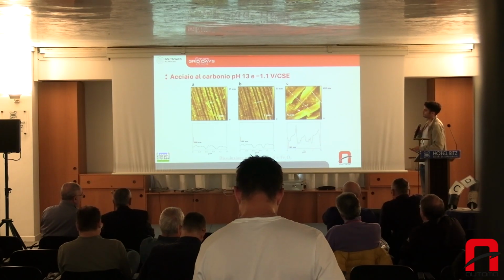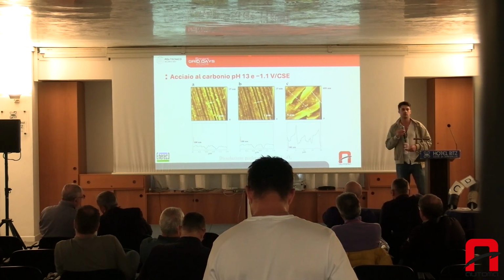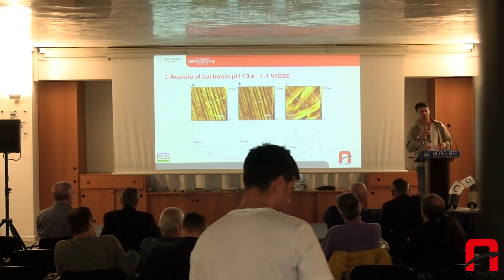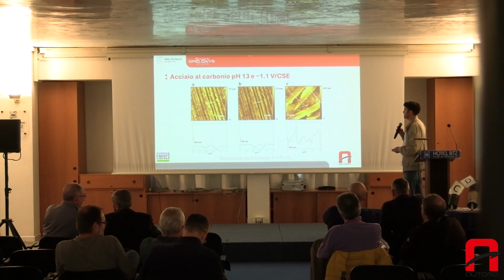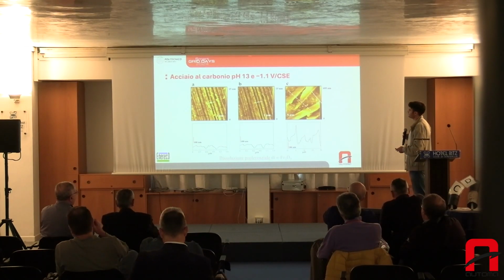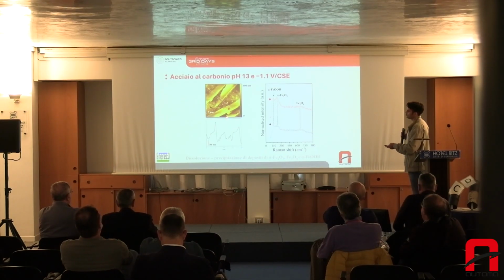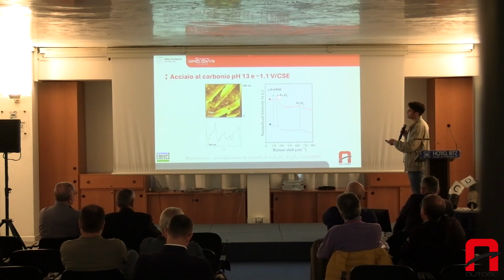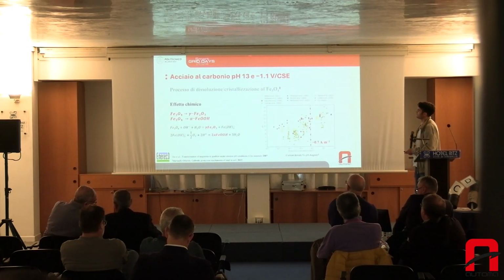If you continue with the polarization, this alkalinization also brings about important effects on the surface. They also expand the specific area of our sample, and in turn, this means a larger quantity of current required. Here we basically used laser on these parts, and they correspond to deposits of hematite and magnetite.